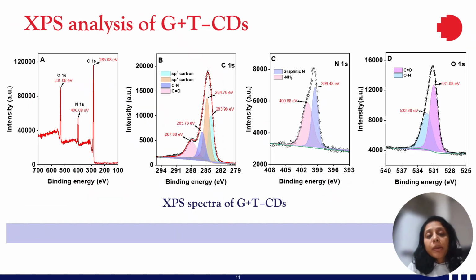To understand the chemical composition of the carbon dots, X-ray photoemission spectroscopy analysis was carried out and is shown here. As we can see here in the survey spectrum, it displayed oxygen, carbon, and nitrogen only. The C1s level analysis showed that there are 4 different kinds of carbon present in carbon dots, and these 4 peaks correspond to saturated, graphitic carbon, carbon nitrogen, and carbonyl groups.